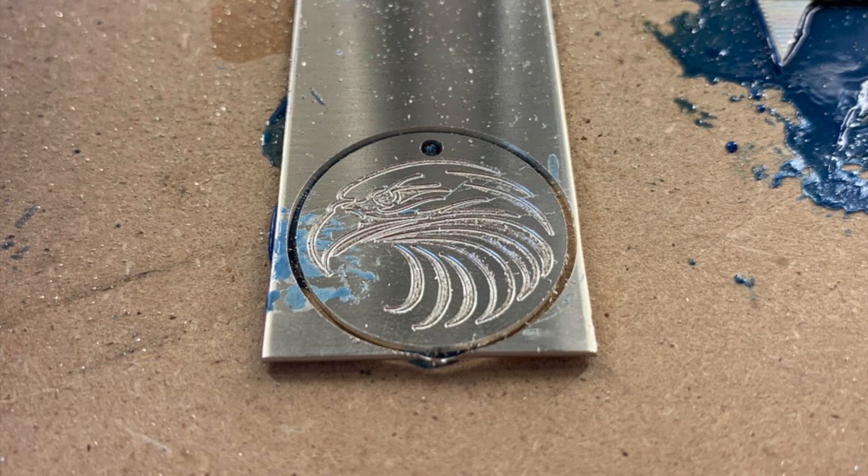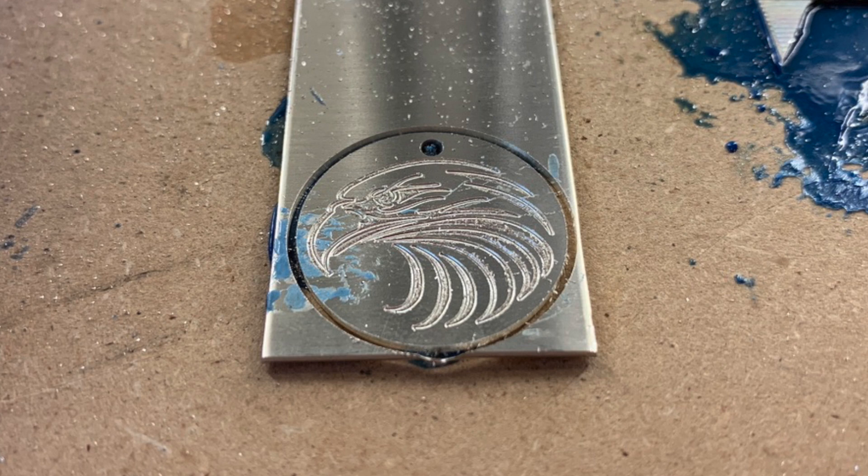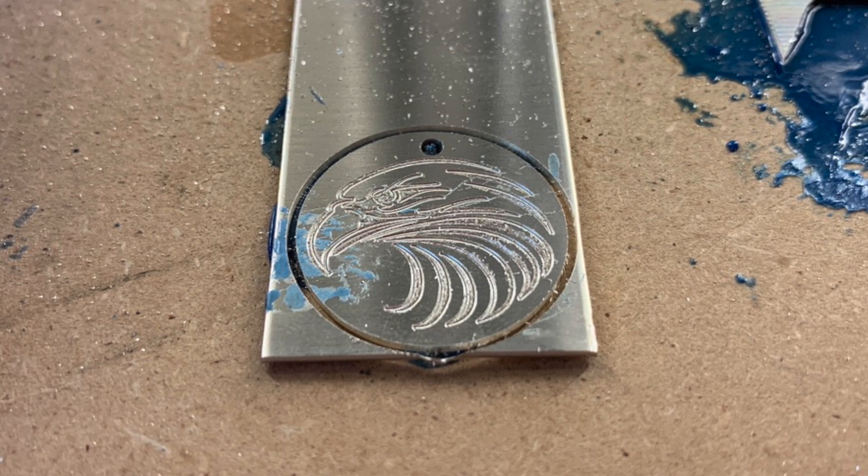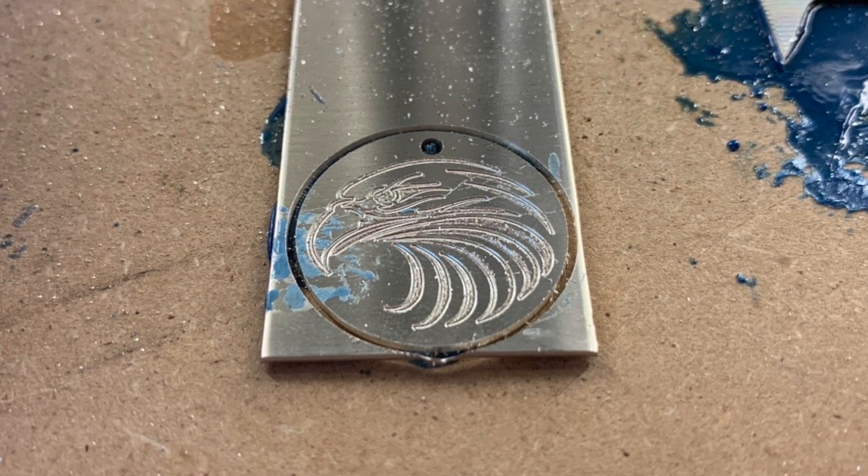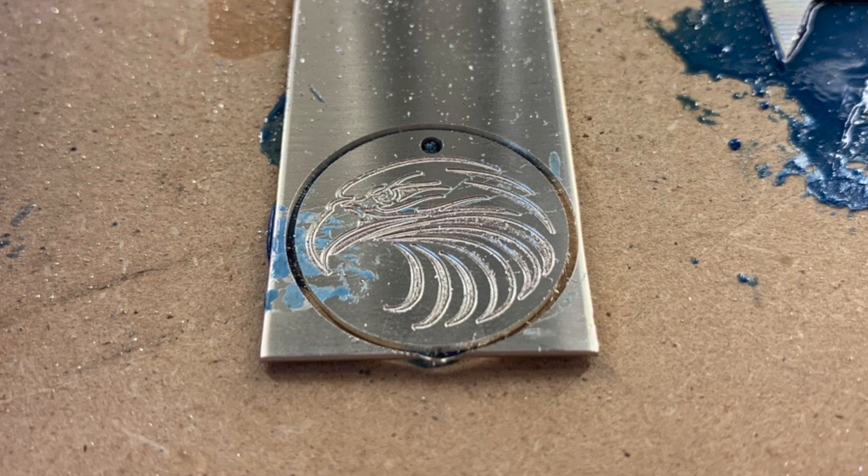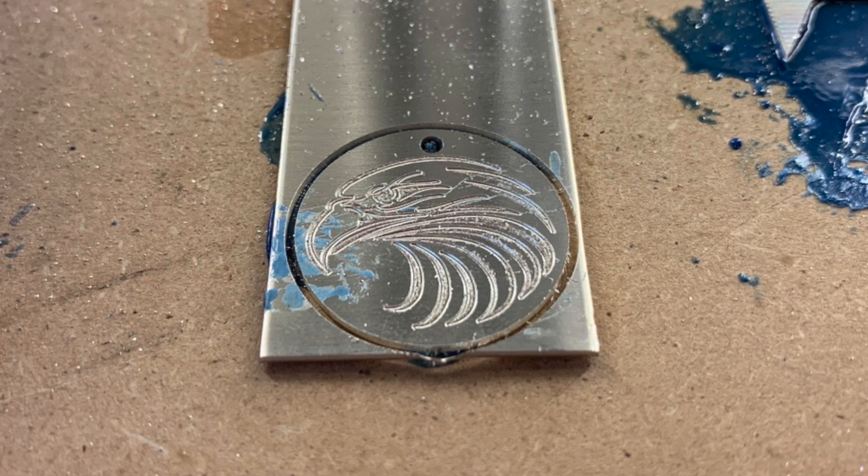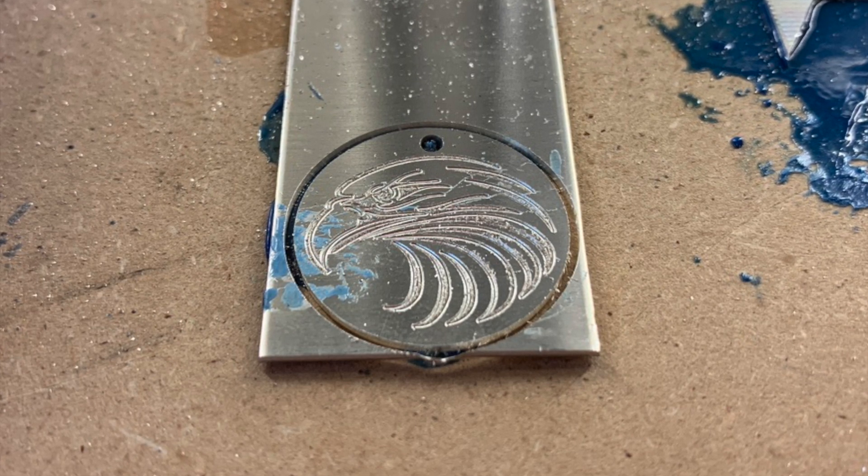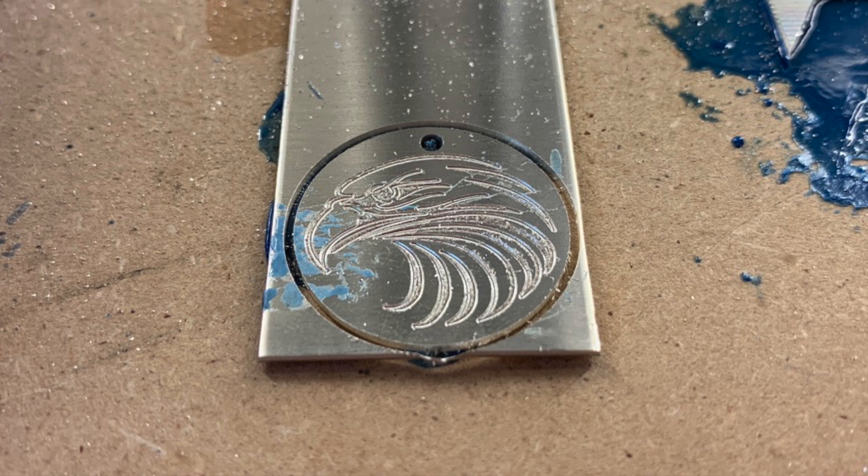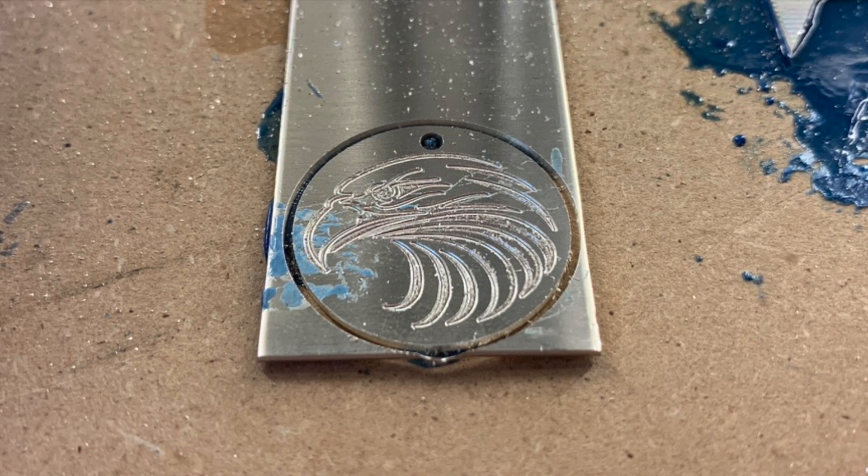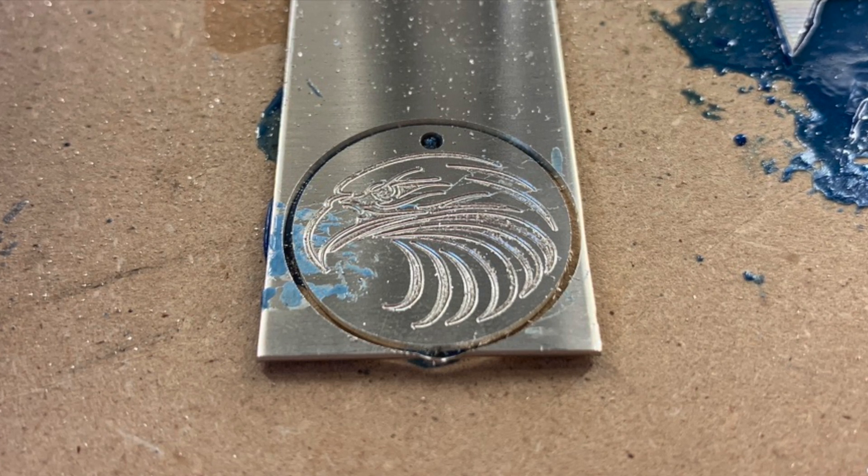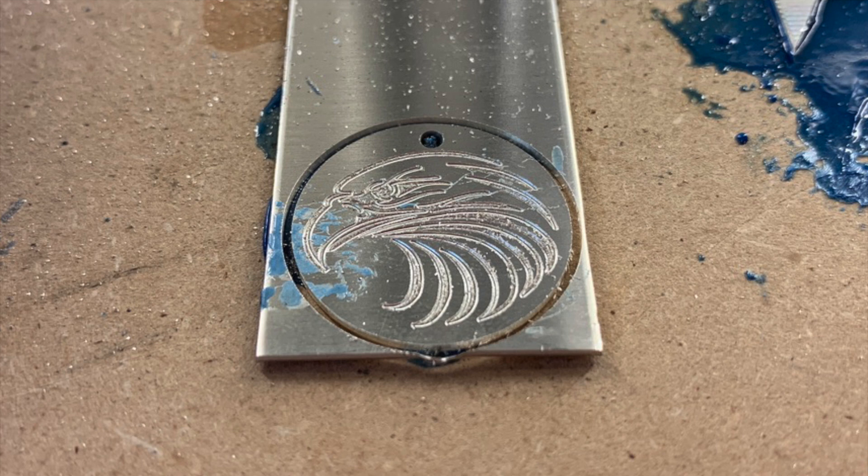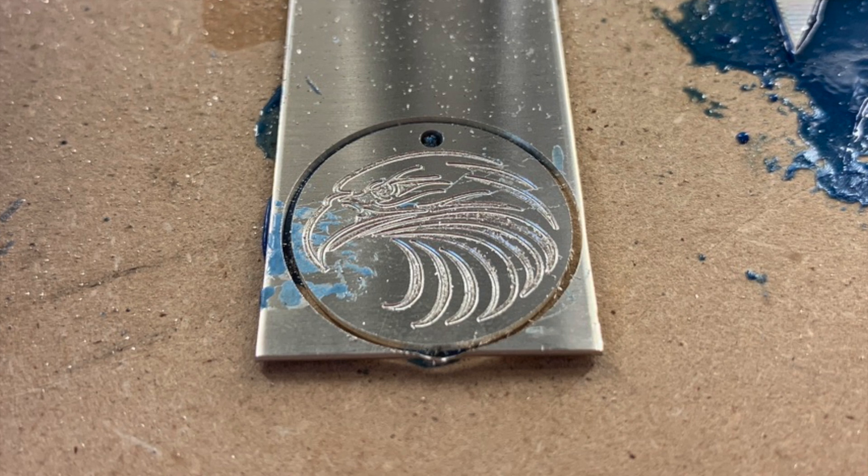As you can see, we traced out the Eagle with this toolpath, but this engraving isn't very clean. There are small shavings still hanging onto the cut walls, and that's because this is dead soft sterling silver. The engraver can't produce chips that break off cleanly. The silver, at a microscopic level, is acting somewhat like clay.